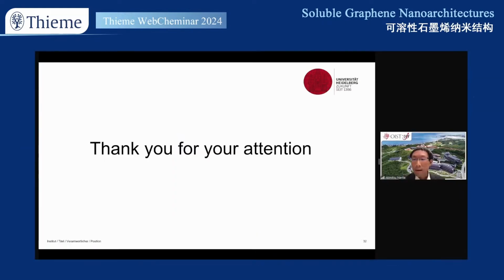So there's already one or two questions from Dr. Soichiro Nakatsuka. The first question or comment is: thank you for the interesting talk. On the stability of other acenes, do other acenes decompose to something or react with something? Acenes basically, when they decompose, they decompose at the non-aza rings, and they typically do so by photooxidation as normal acenes do. So in that way, they are very similar to normal acenes. Does that answer your question?